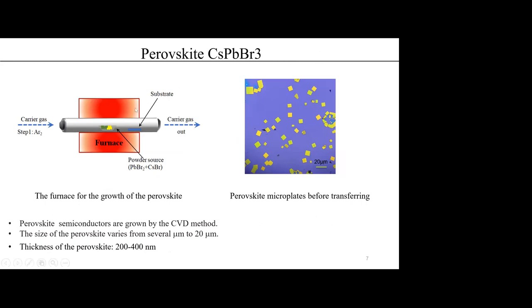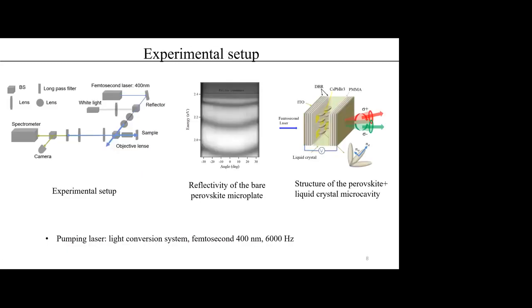The perovskite microplates are grown by the CVD method using some powders under the flow of inert gas at high temperature. This graph shows the perovskite microplates after the growth, where we can see the size of the perovskite varies from several micrometers to maybe around 20 micrometers. The thickness of the grown perovskite microplates is not constant, which varies around maybe 200 to 400 nanometers in our experiments. So this is the experimental setup we used.